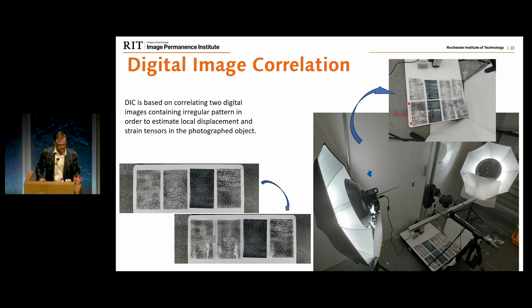Initially, before we cast our own large sheets of cellulose acetate, we simply grabbed the commercial one, which, as I said, is supposed to be 100%. It's definitely not 100%, but I guess that's the consumer protection for you. What we've done with them is we've taken three: this is triacetate, these are diacetate sheets. And you can barely make out a large painted cross, a smaller painted cross, and no cross at all. And DIC, for those who don't know, works by taking images of an object that contains an irregular pattern at certain periods of time, and comparing those images; shifts in those irregular patterns allow you to calculate strains.